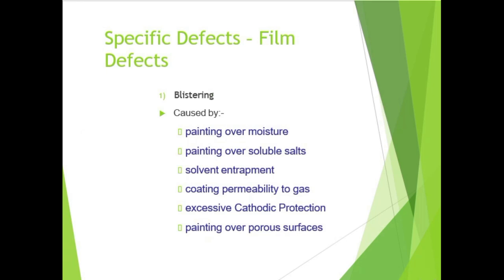Specific film defects: blistering is caused by painting over moisture, painting over soluble salts, solvent entrapment, coating permeability to gas, excessive cathodic protection, or painting over a porous surface.